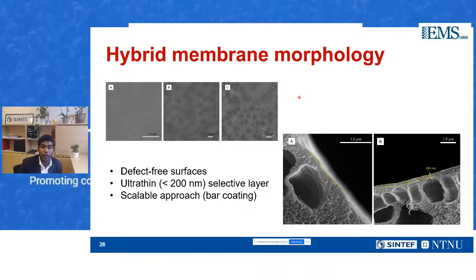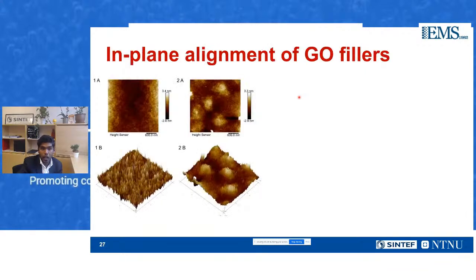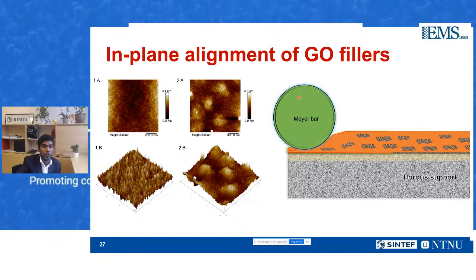cast it into a very thin selective layer on top of a porous support. Thanks to the very thin structure of the 2D materials, we were able to coat an ultrathin selective layer, less than 200 nanometers, using a scalable bar coating approach. The other thing we found is that 2D materials like graphene oxide tend to align themselves so that the plane of the graphene oxide is parallel to the plane of the membrane support or the selective layer. The reason is the surface phenomena that we use for coating the membrane matrix.